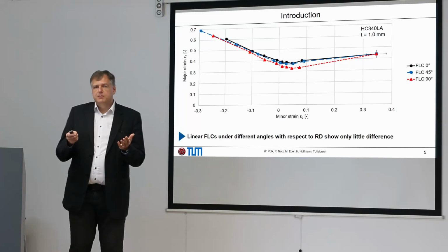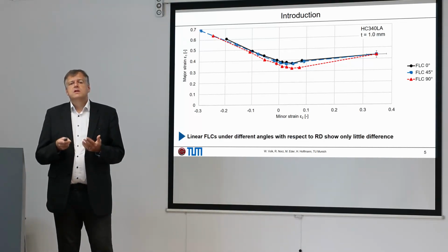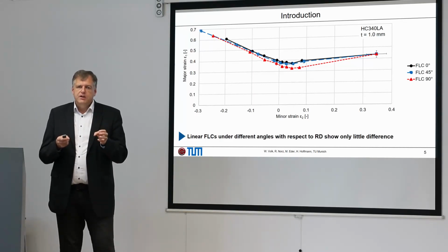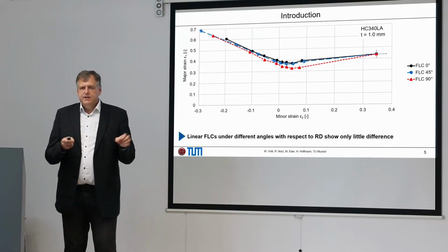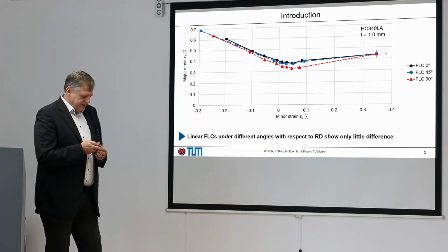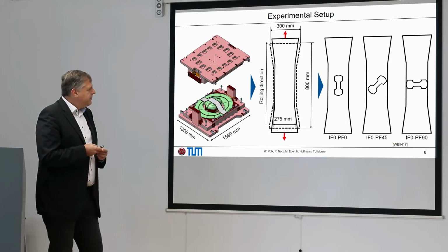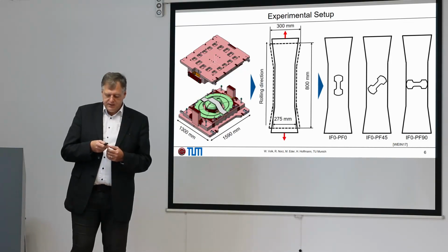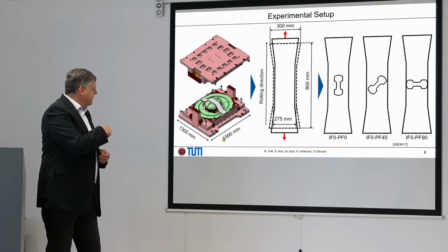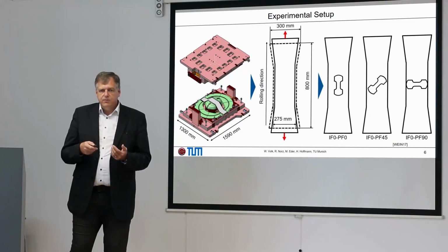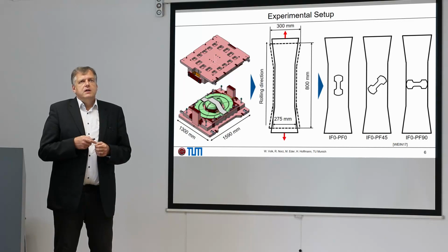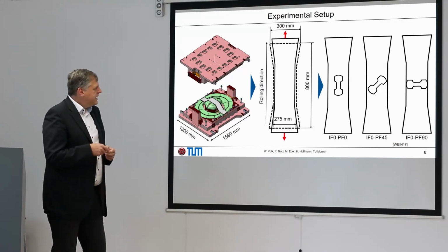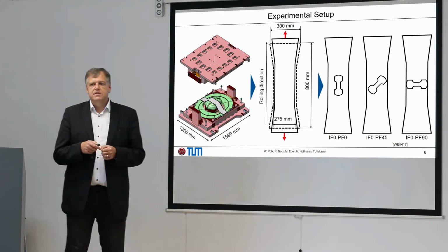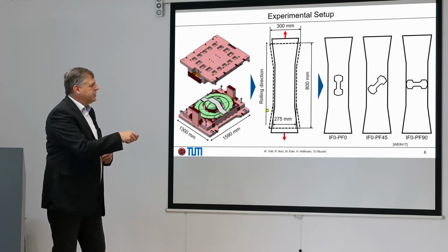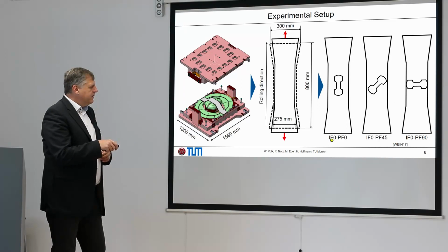Now, as I mentioned some minutes ago, our main goal is to describe the behavior when changing the loading direction within a non-proportional load path. There, it's necessary to have a suitable test equipment to realize this, and this is available at our institute. It's an oversized Marciniak test, as you can see here, with the big dimensions of 1,590 by 1,300 millimeters. And the dimensions are chosen so that even when we have uniaxial strain, it's possible to cut out secondary specimens where we can also totally change it with respect to the rolling direction. Here we see also the names for it.